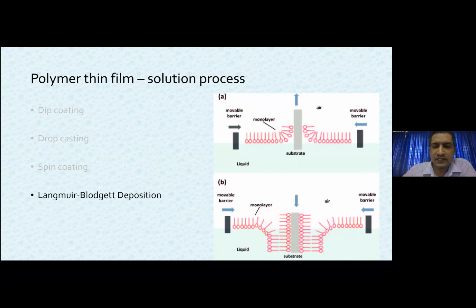A slightly more complex method is the Langmuir-Blodgett deposition method, where you try to make a monolayer of, let's say, an amphiphilic molecule at an interface between two different phases of different polarity. Usually the liquid chosen is water, and then you have air. The amphiphilic molecules align in such a way that the hydrophobic part tends to be exposed towards the air, while the hydrophilic part tends to be in proximity to the liquid surface, generally water. Then you slowly move the barrier, generate the single film, and then move the substrate from the middle, and you have a single layer of this amphiphile coated onto it. This is the Langmuir-Blodgett deposition method.